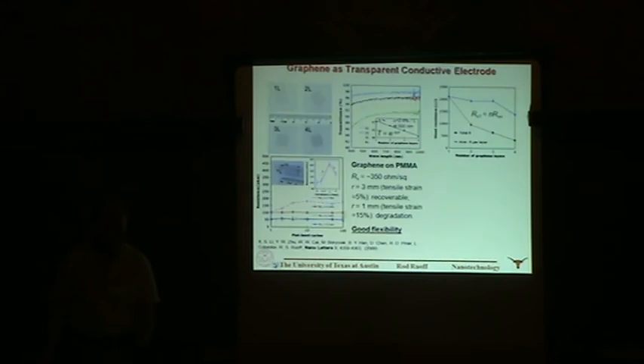And so in this experiment here, he's showing that it maintains a resistance that we can measure even when it's highly curved, simply applying it. And then by using ellipsometry, we could measure the transmittance as a function of wavelength and as a function of the number of layers.